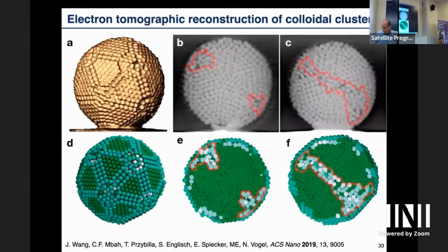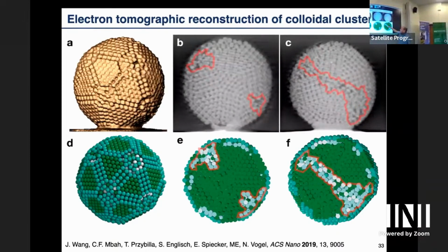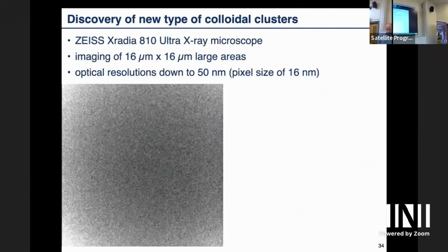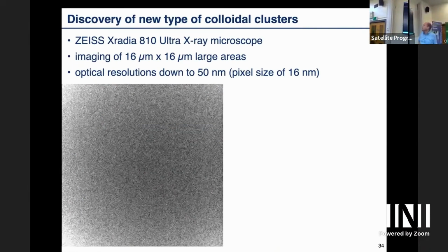And we can analyze that in an experiment as well. So here is electron tomography analysis of such non-magic number clusters. We now see the defects here in the wedge. We can compare that to our simulation, and it works pretty nicely. So that means we can understand the complete range of magic number and off magic number clusters. And here's another video of the actual tomography.